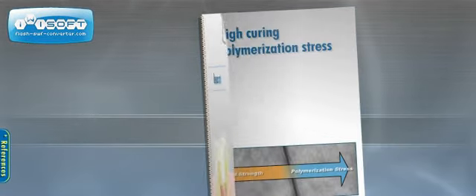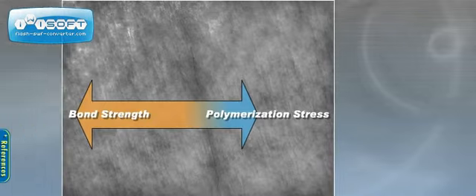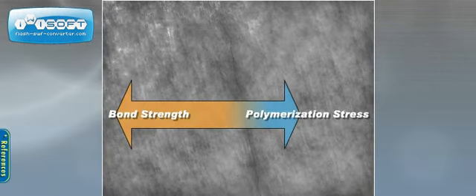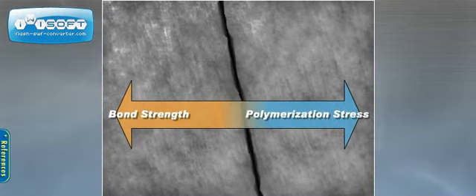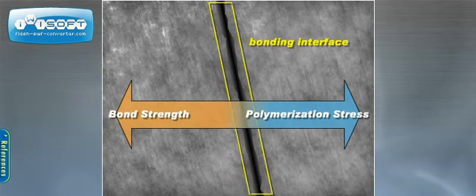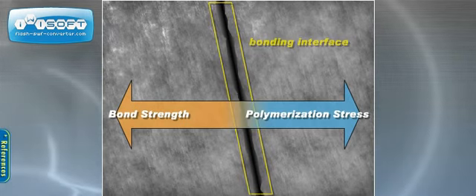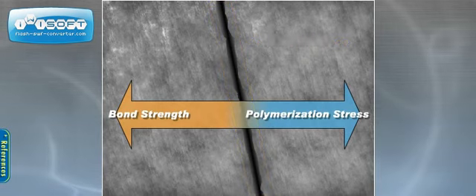Research has shown that high curing polymerization stress is a relevant contributor to clinical symptoms such as cusp deflection, enamel fracture, and postoperative sensitivity. In fact, the internal stress generated within the composite during polymerization is considered more important than the actual shrinkage within the cavity preparation because this stress may linger and/or be readily transferred to any bonded surface.